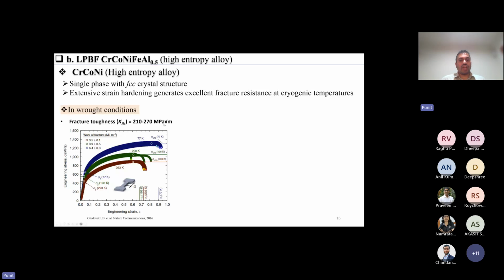Although this material shows excellent fracture resistance because of this sequence of deformation mechanisms, where you have dislocation activity, then you form these nano twins and stacking faults, and because of that you have large crack tip blunting happening, which gives you such high fracture resistance. The problem with this alloy is that it has a yield strength which ranges from 415 megapascal to around 625 megapascal even at cryogenic temperature, and these strength values are somewhat similar to stainless steel. And stainless steel also has a fracture toughness around 200 to 250 megapascal root meter.